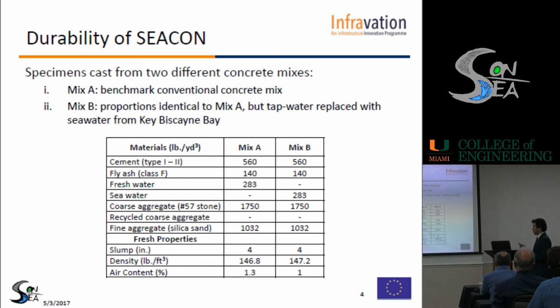And then what we did for mix B, which is our seawater concrete, is we just replaced the fresh water in the conventional concrete with seawater. That's the only difference in mix B. But for sure, because of the chloride content of your seawater, it's going to affect your setting time. So you have to use different kinds of admixtures, mainly retarders, to control that, and you can easily do it.